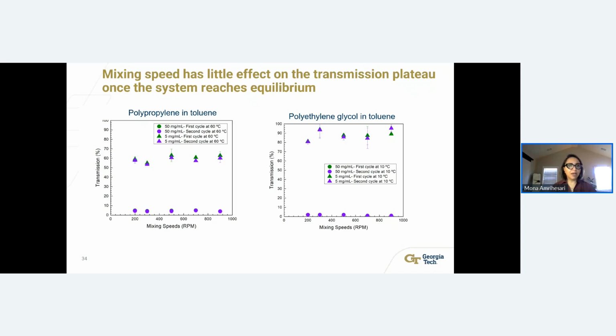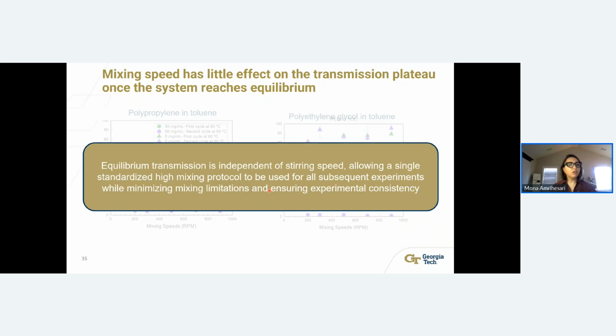Next, we looked at another parameter, which is mixing speed, which has little impact on the transmissivity plateau value as the system reaches equilibrium. These are, again, the same model polymer systems, polypropylene in toluene and polyethylene glycol in toluene. And we see for 5 milligram per milliliter and 50 milligram per milliliter, the transmissivity is very consistent and there are no statistically significant changes. So we concluded that this equilibrium transmission is independent of the stirring speed.